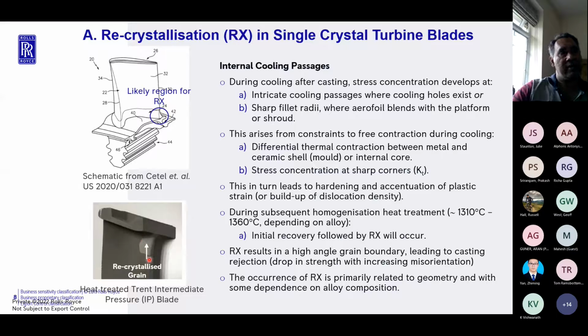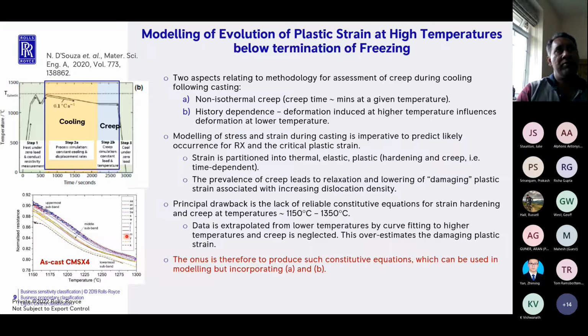So it's important for us to define the critical conditions where these recrystallized grains form, but also, at the same time, we should be able to model these. So modeling is key. Like I said, the process modeling group exists in Rolls-Royce, and one of its key jobs is to model such defects so that you can engineer around them and effectively not have high non-conformance. So modeling of the evolution of plastic strain during high temperature freezing of a turbine blade is quite important. One of the main reasons being that it relates to the role of recrystallization.